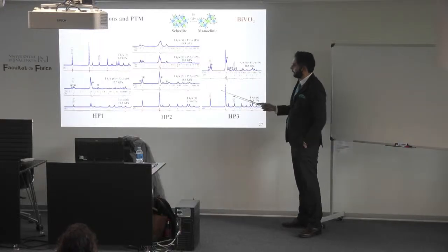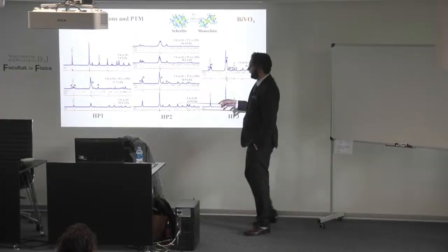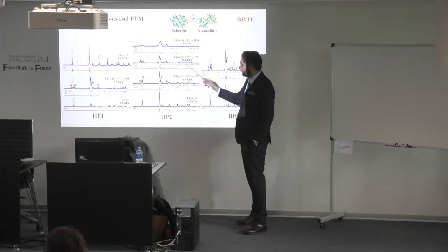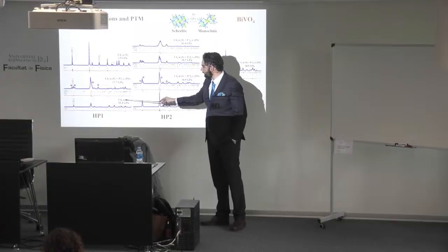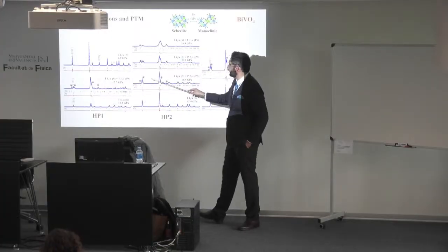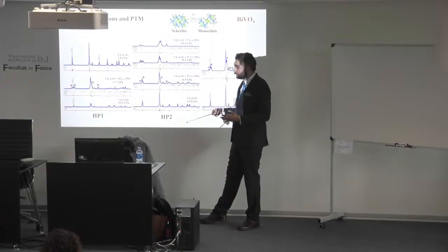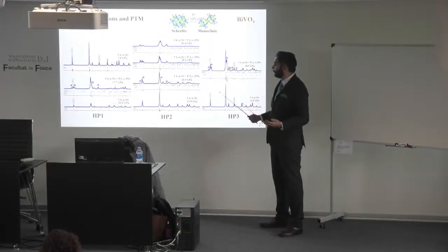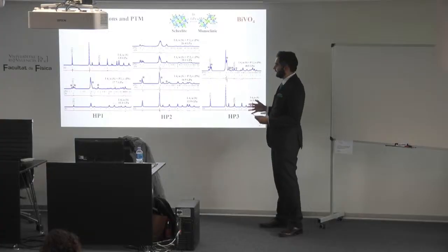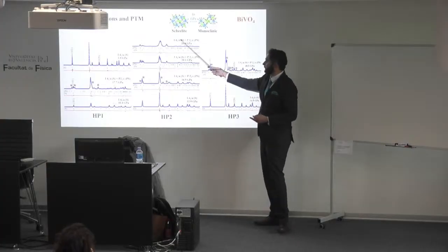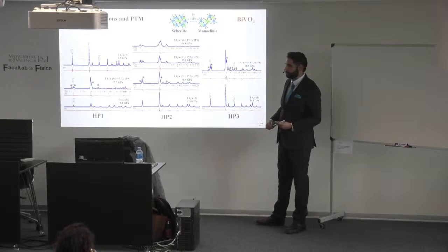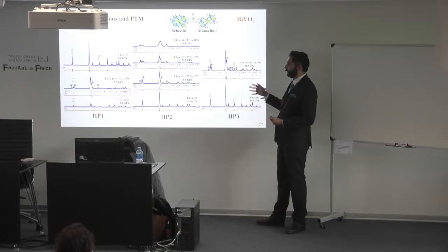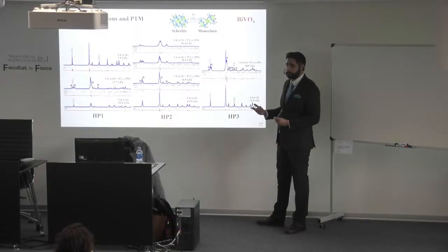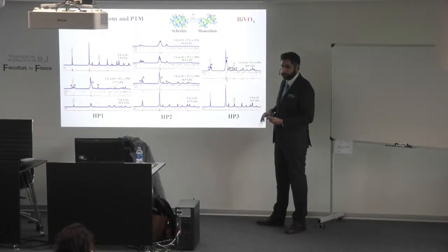Just to mention this last phase transition, in this case, at around 16 GPa, we had the scheelite, and then a lot of extra peaks were adding to the scheelite ones. And we do the best to fit this. In this case, it was relating this structure with other materials in order to see which structure would be the best. There's also some other works in bismuth vanadate that proposed other phase transitions that are different from this one, but this is the best that we got.